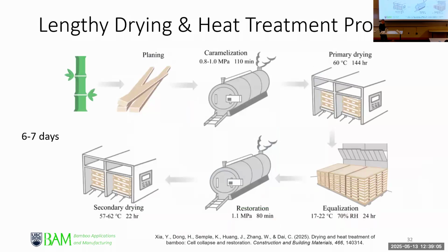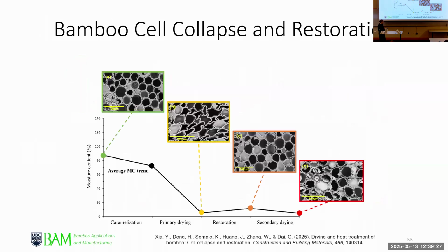And the other hurdle with bamboo is the drying, like I said, because of the low permeability, it takes much longer to dry. It's hard to believe that simple strips like bamboo take even longer for us to dry than a 2x4. 7 days. So one of the reasons Monica did the study is that it's again to do with the low permeability, but also the soft tissues. Remember the sponge? It tends to actually collapse when